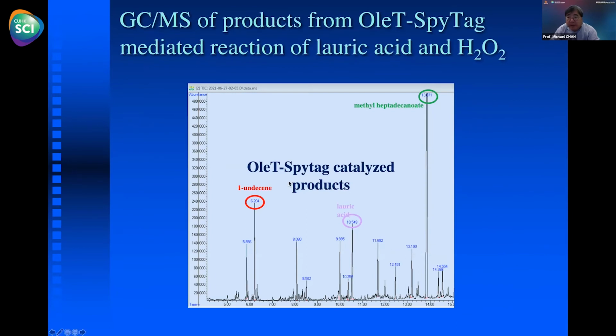Okay, so here's the mass GCMS result for the OLET SpyTag. You can see after incubating with OLET SpyTag, we incubate lauric acid, we decarboxylate it, it will become undecane. Here's the standard. And you can see we get quite a bit of undecane, more than if it's not definitely linked, but you can see we get a lot of undecane, undecene, sorry, enough that we can detect it in good amounts.